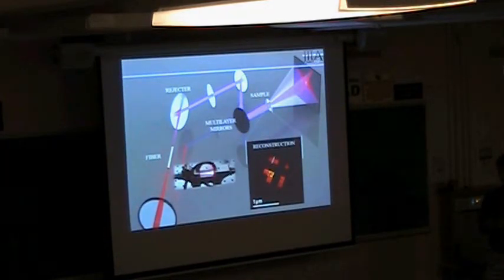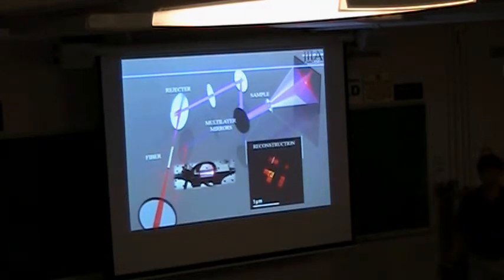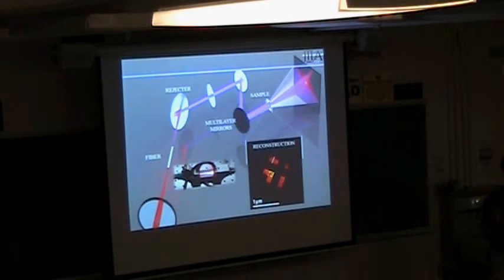You can make a 70% reflectivity, 0-degree incidence mirror for 13 nanometer light by having these like 5 to 10 nanometer layer stacks. And we use these multi-layers to select a single harmonic and also to focus the light down onto the sample and make efficient use of all of our photons.